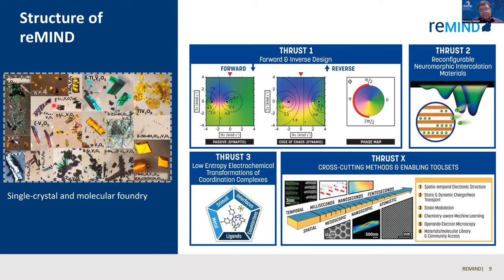So I wanna say, and I think there's a tremendous opportunity for collaboration here as soon as y'all are up and running again, one of our distinctive features: Remind focuses on two classes of materials, intercalation materials, so strongly correlated transition metal oxides with the potential for ion intercalation, and then also redox active coordination complexes that have redox cascades. And in both cases, we've got this tremendous, very unique capability. We have very large crystal foundries. So that means that we've got single crystals of these. We have the ability to grow single crystals, which you can then of course section or use as is.